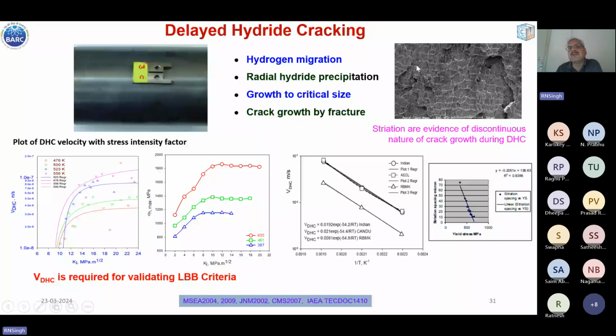And this bright region is because of the ductile tearing of the matrix, and the dark region in between is because of the cleavage of hydride. So here, if hydride and matrix had debonded on the fracture surface, at least in some portion we would have got only bright region, but this is not the case. So this suggests that it is the hydride which cleaves apart, and debonding of hydride and matrix does not take place.